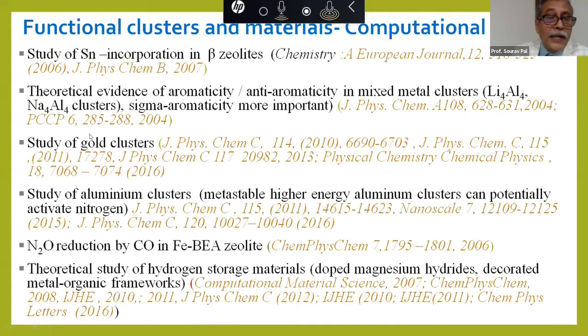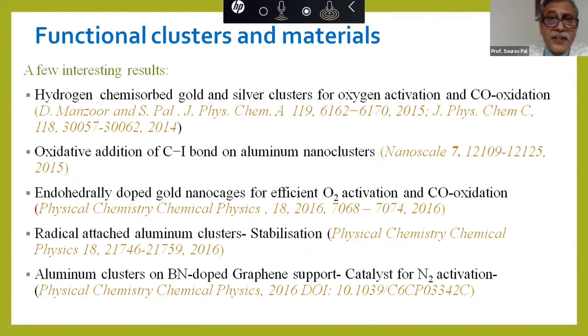I'm going to only go directly to some of the work like gold clusters, aluminum clusters, and so on, and a little bit about hydrogen storage. So a few interesting results in the gold and silver clusters. Again, here, I will only tell the outcomes. And the methods are, of course, DFT. I must say here that we have done mechanisms in many cases to find out how the clusters are catalyzing the reactions.